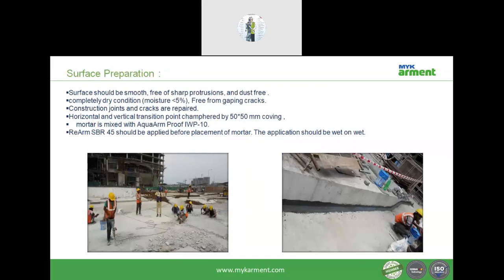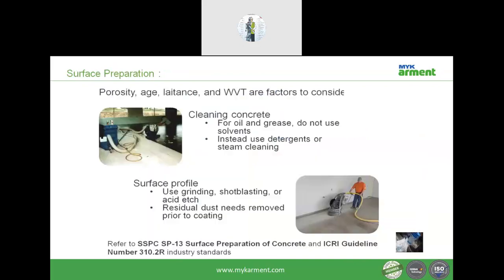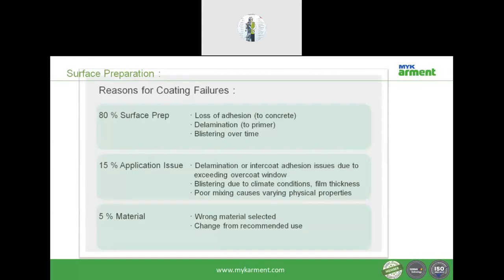This is the application procedure. This is the surface preparation, but we need to be very clear that the moisture should be less than 5%, and then all the joints have to be treated, and if there are any cracks, they have to be treated. The most used system is surface grinding. At certain places they also use the shot blasting system to remove the damaged concrete and to give a better surface. Now, the reason for a coating failure: 80% would be on surface preparation, 15% on application issues, 5% on wrong material selection.